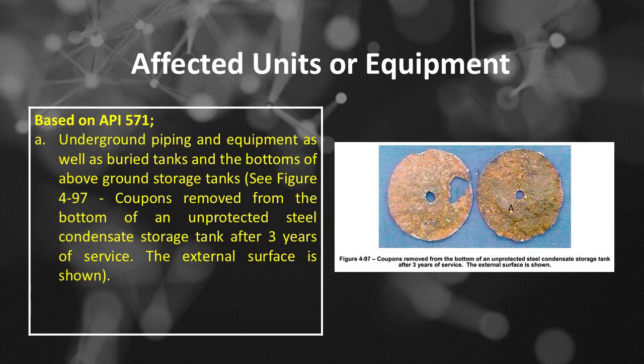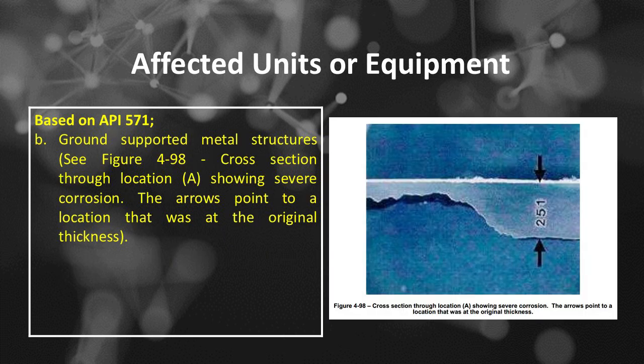Soil corrosion damage affected units or equipment based on API 571. Number A, underground piping and equipment as well as buried tanks and the bottoms of above-ground storage tanks. See Figure 497, coupons removed from the bottom of an unprotected steel condensate storage tank after 3 years of service. The external surface is shown. Number B, ground-supported metal structures. See Figure 498, cross-section through location A, showing severe corrosion. The arrows point to a location that was at the original thickness.